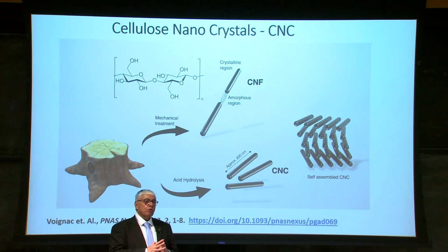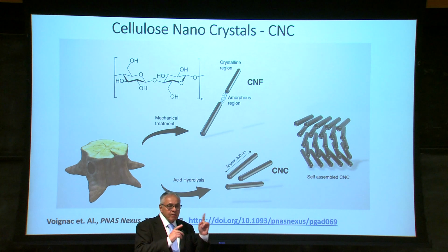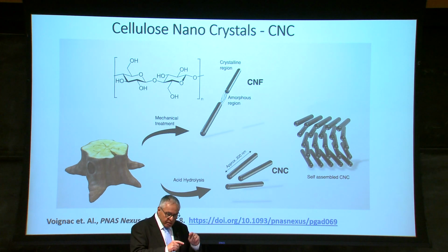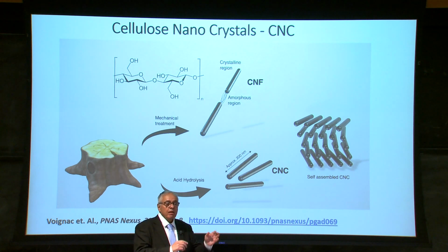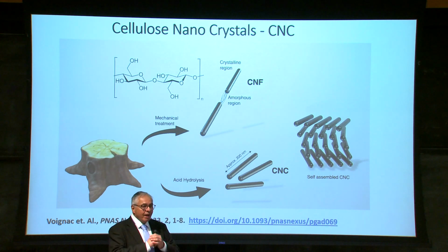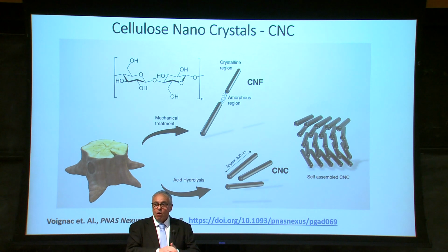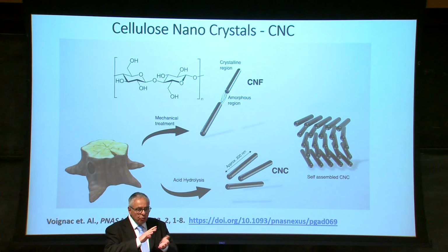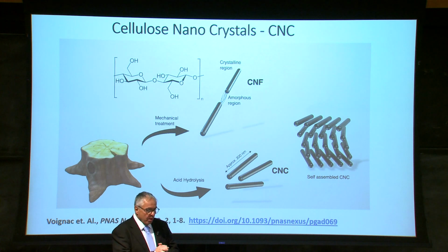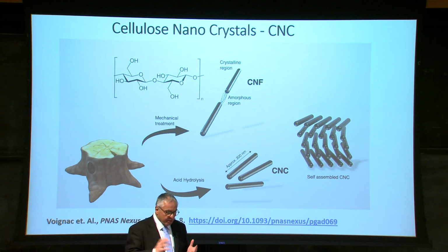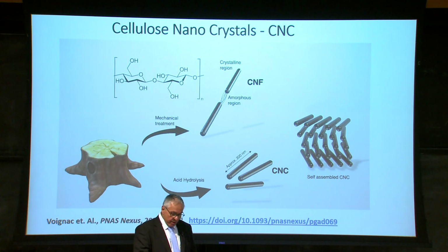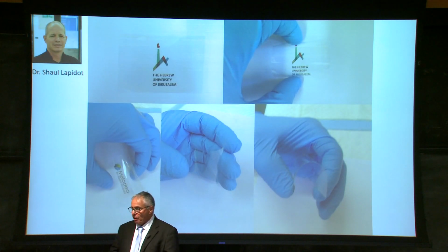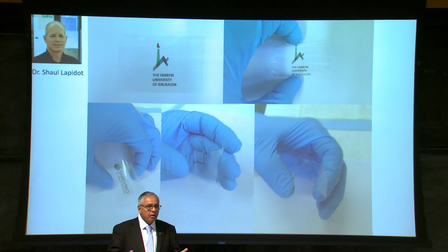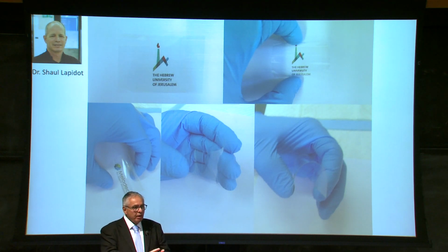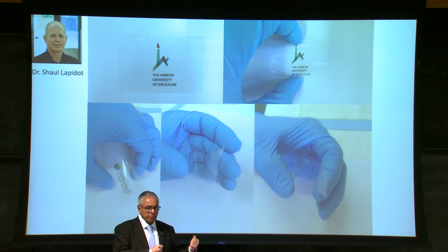Well, one very interesting feature of cellulose nanocrystals, unlike CNF, okay, this is cellulose nanocrystal is CNC. CNF is cellulose nanofibers. The cellulose nanocrystals actually form a chiral nematic liquid crystals. Once the concentration is anywhere between 2.5% and 3% in water. So that's beautiful because once you apply these cellulose nanocrystals on any surface, it can be paper, it can be concrete, it can be wood, whatever, plastic. Once the water evaporates, it self-assembles into a very strong and transparent film.